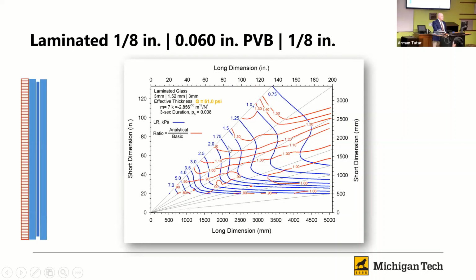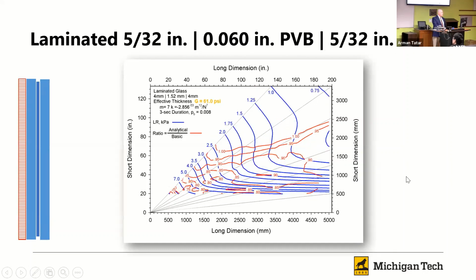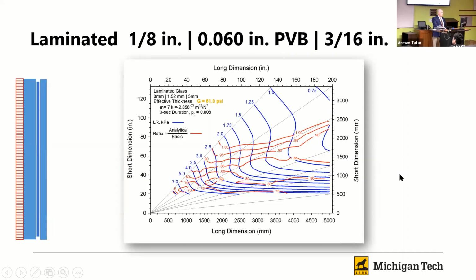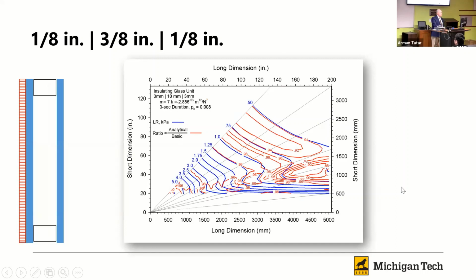If we compared the laminated glass to the charts, we see that the effective thickness model overestimates the strength of our laminated glass for aspect ratios around 1, so up in this upper region of my chart. So that's not ideal. There's some issues there. We can play around with different constructions. We see in some constructions, asymmetric, it actually shows that it's weaker in some cases, parity in others. And if we go to insulating glass units, we see that those are relatively close for symmetric, because we saw when we did our example that the load share was close to 50%. It wasn't that far off, so we don't expect these to move around much.